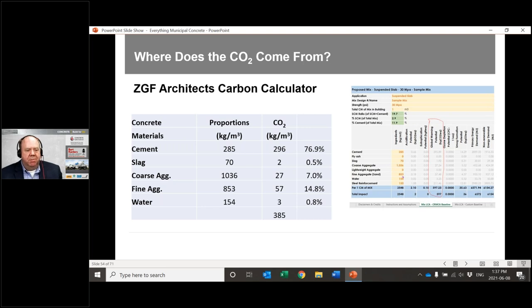If we look at the GU cement, 285 kgs, it's basically one kg of CO2 for every kg of cement that we're putting in. So this is driving it. We look at slag. So slag is produced locally here in the Ontario marketplace. It's a byproduct from the steel industry. Because it's a byproduct from the steel industry, the only CO2 contributions that have to apply to concrete relate to the processing that we have to do to use it. So the CO2 impacts of producing steel are tied to steel. The waste product that's left over from the steel industry, we have to grind down into a small particle size so that we can use it. So we have to account for the processing and we have to account for the trucking back to the concrete plant. But it's significantly lower than the impacts from the GU or the GULs.